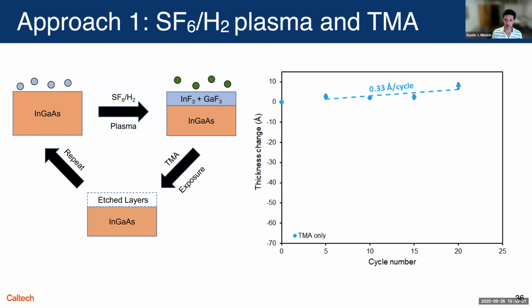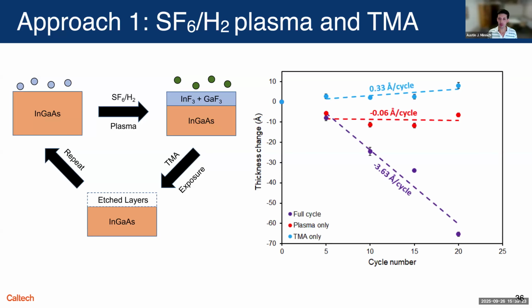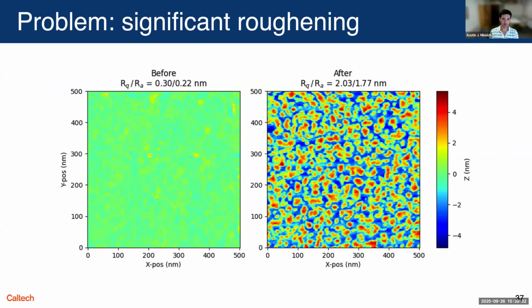And this is a plot of thickness change versus cycle number. A key requirement of ALE is that each half step should not etch, but when you combine them, they should etch. So this is a plot of only TMA, and there's no etching. This is a plot of the plasma step only, and there's really not a whole lot of etching. And then when you put them together, you do see some etching. These are not the cleanest data, but as it turned out, this process had other problems. Namely, it caused significant roughening of the surface if you compare the right plot to the left. So this wasn't so suitable for our purposes.